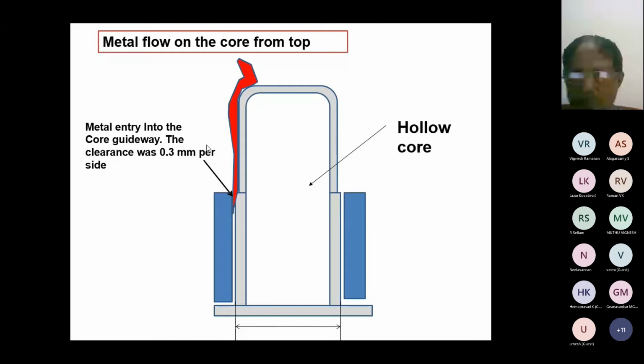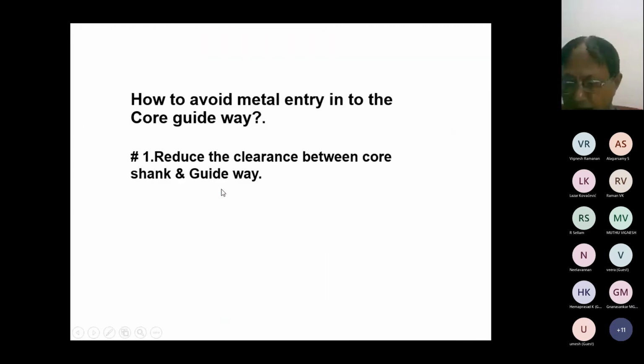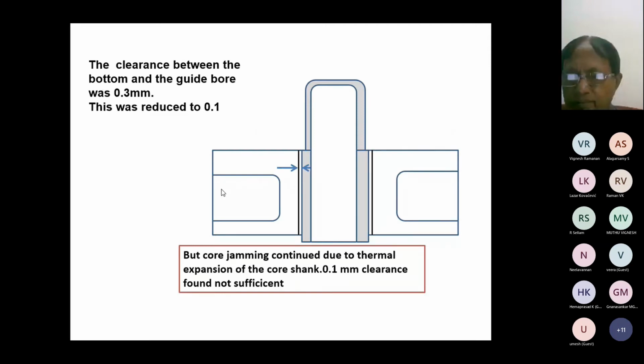So instead of metal going straight away into this area, why not we make it diverted by 90 degrees? So we made a core. Then we tried to make the clearance only 0.1. 0.1 did not work. Again the core jammed, but no metal entry. The problem is you can't operate it because after 2 to 3 hours, again, due to core expansion, the core jammed. So 0.1 clearance did not work in this area. Although the metal has not gone, it has not worked well.